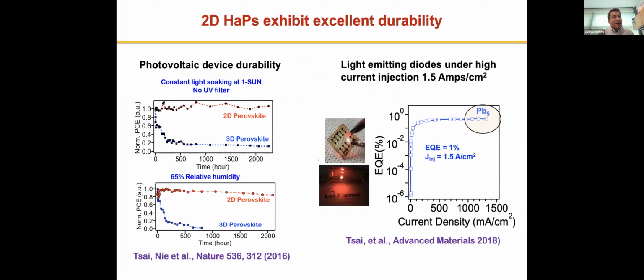And so, when we started really working on these, this is the first work that came out of the 2D perovskites, where we showed back in 2016 that the 2D perovskites exhibit much superior durability compared to the 3D perovskites, both under light illumination, and this is a device which went up to about 2000 hours, and also under humidity. Now, in addition to this, if you take the same device and drive an LED and pump a lot of current into it, you can get the LED to operate at about 1.5 amps per centimeter square, which is quite large. And you can see that you still don't see a degradation in this curve.